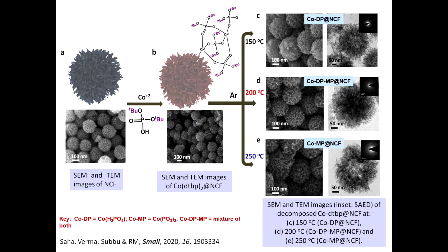As luck would have it, the best catalyst turns out to be the one which is the mixture of dihydrogen phosphate and metaphosphate. Don Tilley, a friend of mine at Berkeley, has worked on these cobalt phosphates, metaphosphate, and written a number of Advanced Functional Materials papers around 2015, 2016, and has batted for cobalt metaphosphate as being the most productive form of cobalt phosphate, which would split water into hydrogen and oxygen. Okay. And this will be an antithesis to his work, although we know each other very well.